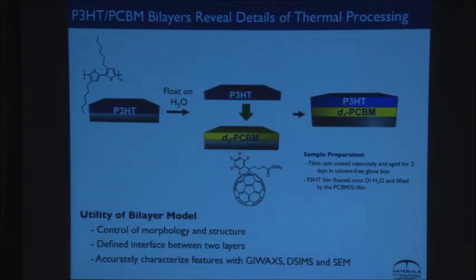And so what we did was we made a classic kind of diffusion couple experiment where we cast a film of a deuterated version of this fullerene, and we float cast, basically we spin coat a film of P3HT. We can lift it off on water and land it and make a very sharp interface there. This is kind of a standard technique in polymer thin film science. We can make this bilayer.